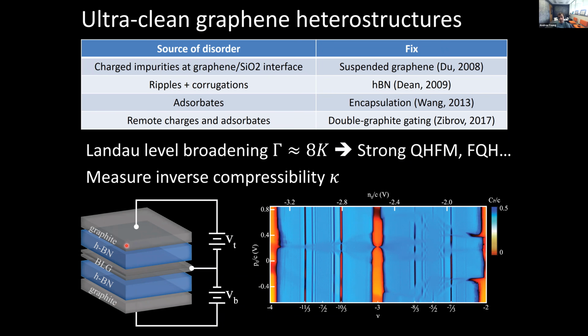measurements of the inverse compressibility, or really they're measurements of the capacitance. So if you have a structure like this, you can measure the capacitance between one graphite gate and the other with the bilayer graphene grounded, and that gives you directly a handle on basically the thermodynamic compressibility, because if this